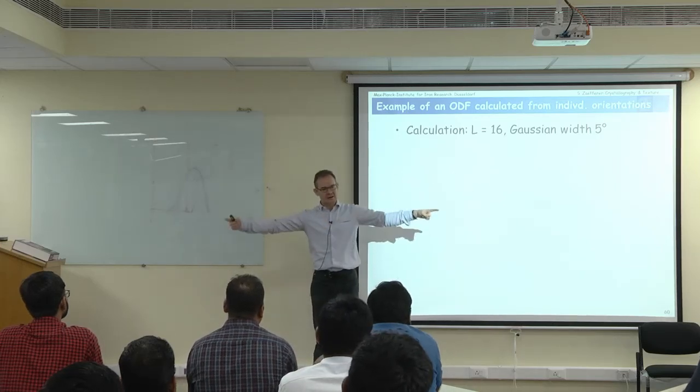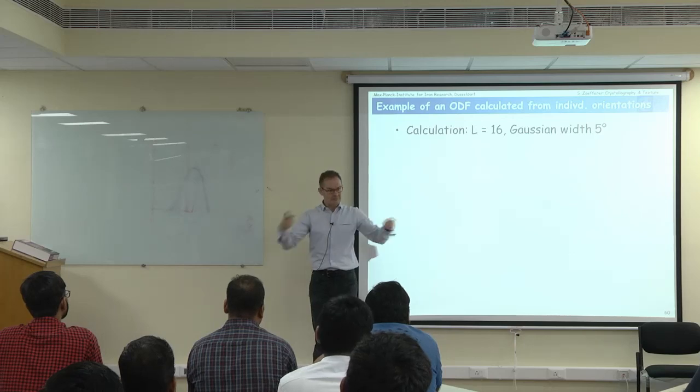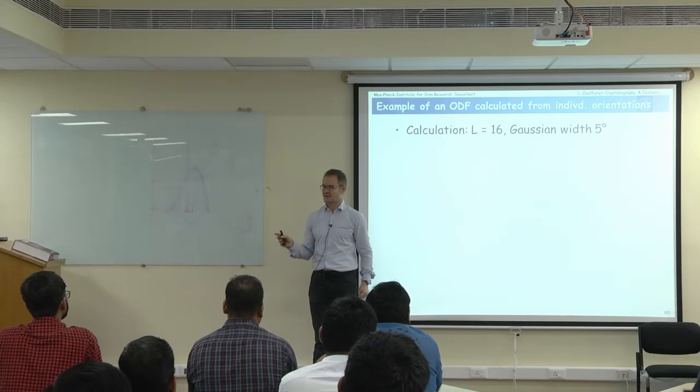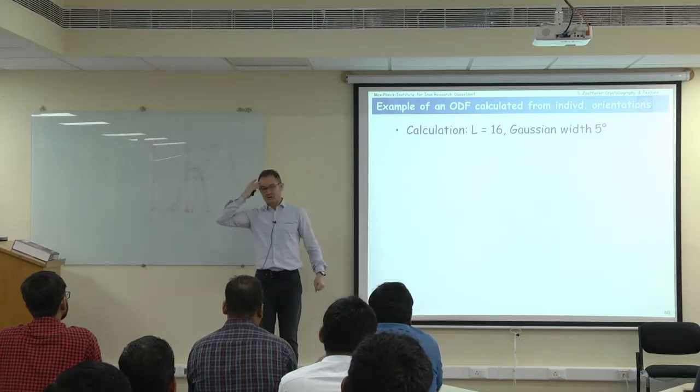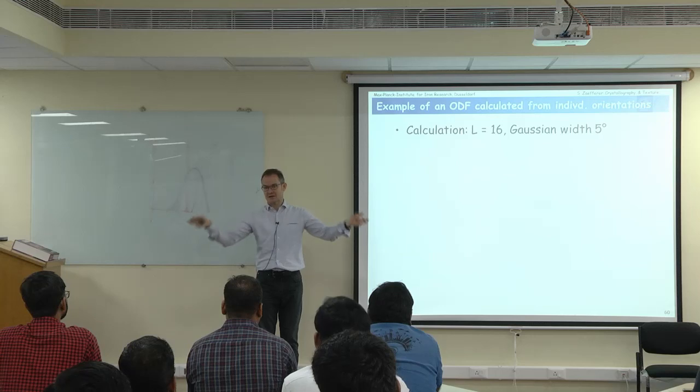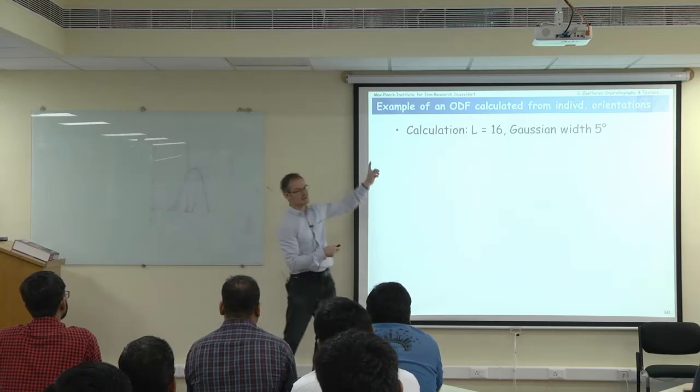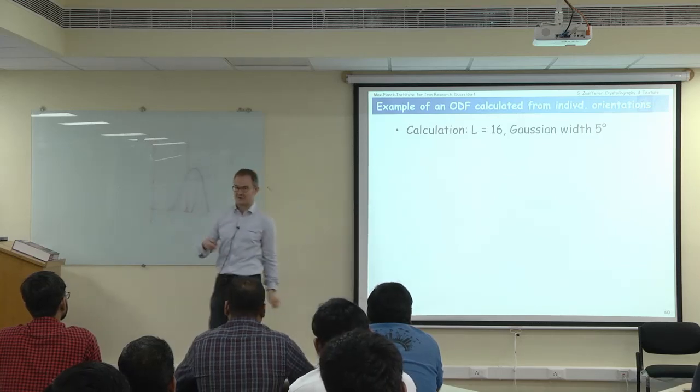And you can imagine the longer I calculate, the more numbers I get, and the calculations become quite lengthy. If you go up to a development degree of 40 or so, it calculates for hours. If you go to 16, it calculates 60 seconds.